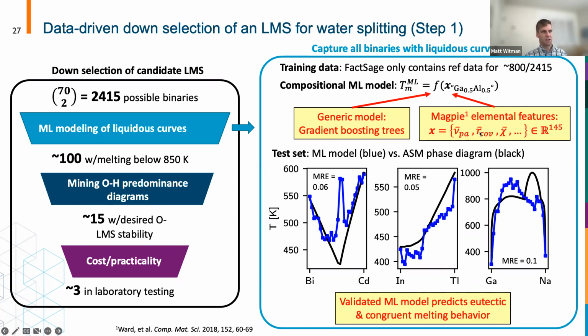This just involves things like covalent radii, electronegativity, volumes per atom of the elemental solids, weighted by their atomic fractions, and then combined in simple mathematical operations. What was potentially surprising is that such a simple featurization strategy allows you to qualitatively and semi-quantitatively get the liquidus curves for holdout set binaries. So these are materials completely outside the train, validation, and test splits. These are ones that weren't in FactSage at all, but we were able to get the ASM phase diagram, for example, to test the machine learning model and its predictions.